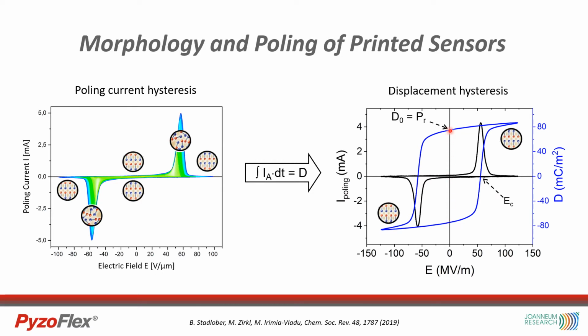From the hysteresis curve, we can deduce the most important key performance indicators of the ferroelectric material sensors, namely the remanent polarization PR, which is the displacement at zero electric field, and the coercive field, which is the field at zero displacement.